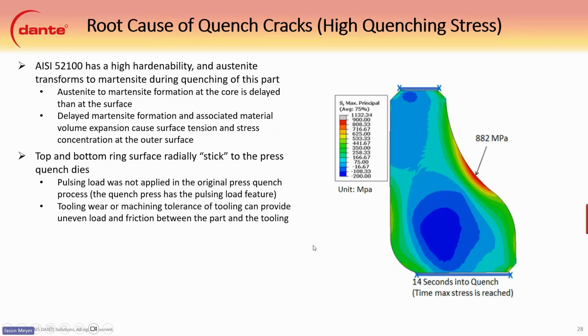So 52100 has a really high hardenability, and the austenite transforms basically only to martensite during the quenching process. In that austenite to martensite transformation, the core is delayed compared to the surface, and this delayed martensite transformation and the volume expansion associated with it causes surface tension and stress in the outer layer, as we were just talking about. For this model, we also used the ring surface on the top and the bottom here.